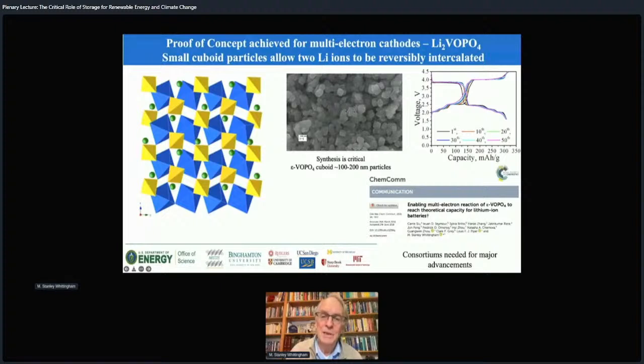These little cuboids are all the same shape. And I show you the electrochemistry on the right here. Remember, we're putting 2 lithiums in. So in here, we're going from vanadium 5 to vanadium 4. Then from vanadium 4 to vanadium 3. If you look at the black line here, this is the first time we cycle it this way, then coming back here. The purple line is the 50th time. So if anything, it's behaving better on the 50th cycle than on the first cycle. So we got proof of concept that we can put 2 lithium ions in a structure without damaging the structure. And in fact, this structure only expands by about 10% when you put those 2 lithium ions in.